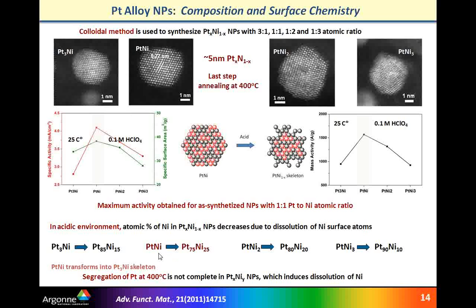And I will pick the one which is labeled here with red color, which is platinum nickel, and platinum nickel after leaching, the bulk ratio or average ratio between platinum and nickel becomes 3x1. But also everybody should remember that this finding applies only to the entire amount of catalyst, and therefore it is still questionable what and how the surface composition looks like. And this is a cartoon which explains that everything which was exposed to electrolyte is dissolved. There is no nickel on the surface.